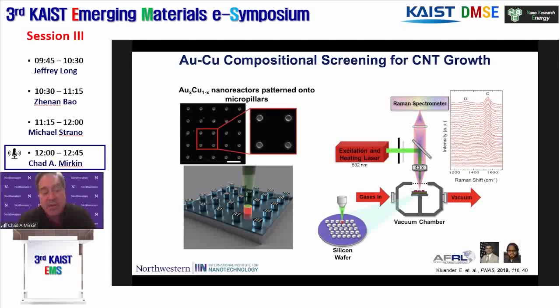How do you screen them? So here we began to collaborate with folks at the Air Force, Benji Maruyama in particular, and his crew. And we moved to them because they had a technique, a Raman technique, that could scan across a substrate and look for signatures of product. And they were interested in making single-walled carbon nanotubes. And of course, it's a great Raman signature for single-walled carbon nanotubes. So we could pattern these types of post arrays with nanoreactors, convert them into a mega library where we systematically changed composition and feature size. In this case, we're looking at gold and copper, and looking at increments in terms of composition and increments in terms of size, going from 1 nanometer to 100 nanometer.